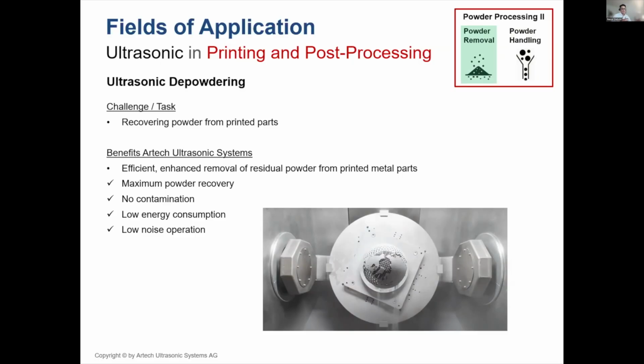So there are different technologies on the marketplace, and nowadays ultrasonic can also help to almost completely remove the residual powder of the printed parts, and thereby the powder recovery can be maximized, again increasing the yield for the end customer. Again, no contamination because the parts are not within the area, very low energy consumption and low noise.